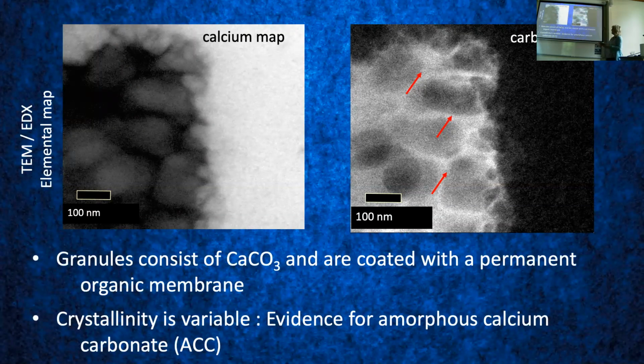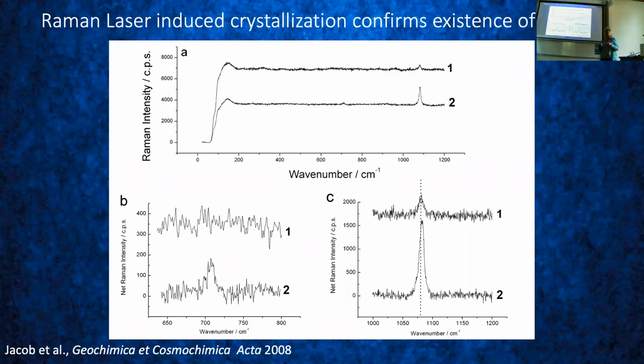But you can see in the TEM, in the transmission electron microscope, if you do a calcium map, okay, here we have all the calcium carbonate around here, not so much here. But in this area where you can clearly see these granules, you can also see enriched carbon around these granules, where there is no calcium but you have carbon, meaning that this is in fact a membrane. What we also found is that the crystallinity is variable within one of these aragonite tablets. We have areas in the tablets that are not crystalline, they're amorphous, and other areas that are properly crystallized aragonite. We found that out with Raman spectroscopy.